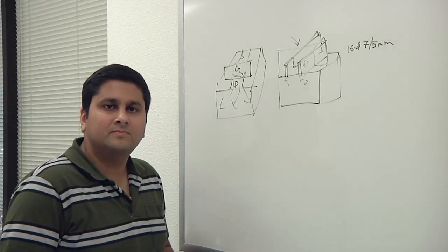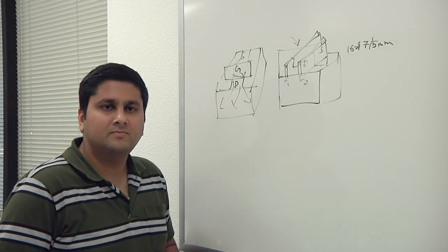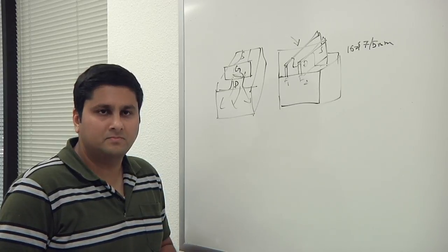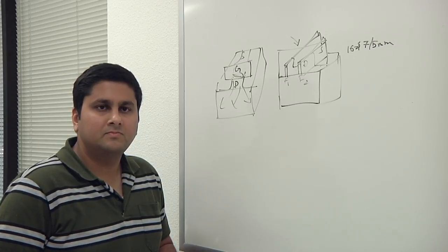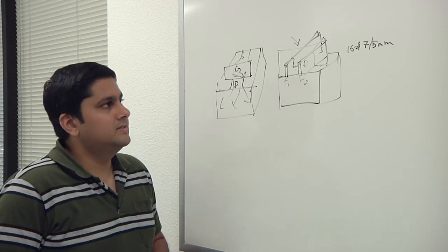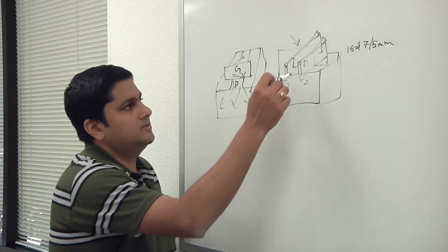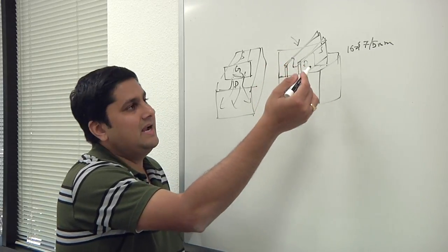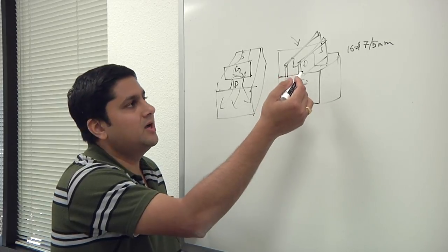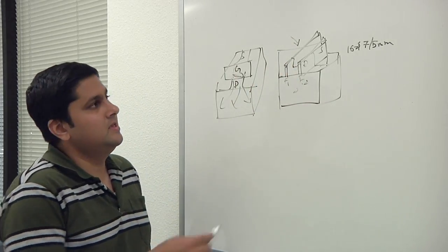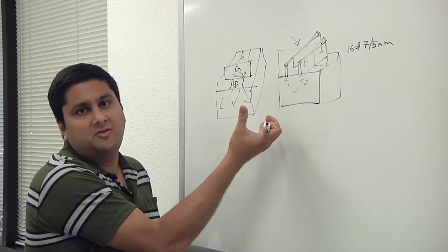And so what you get out of putting in higher fins and actually more fins is better control of the gate structure, but you don't necessarily reduce the heat in that because of the dynamic current, right? That is correct. So in fact, it is going to make it worse, because these raised diffusions are going to be surrounded by dielectrics, and dielectrics have very poor thermal conductivity when compared to silicon substrate or when compared to the metal interconnects. So this essentially forms like a heat trap.